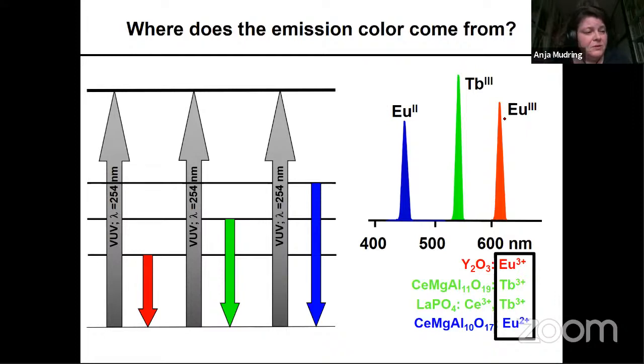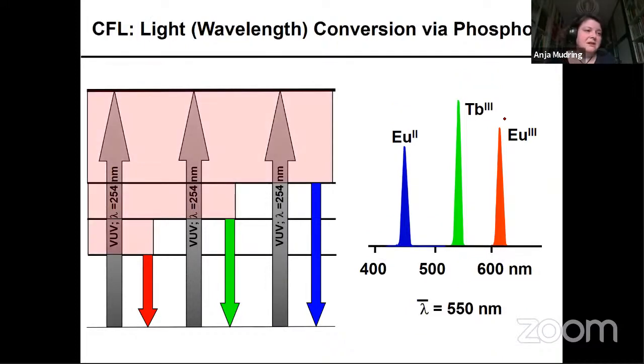And when you look at this scheme alone, you see, and I try to depict it somewhat graphically, you're converting high energy UV radiation into visible of longer wavelengths. So you're essentially losing a lot of the energy you've put in. Here shaded in red. The worst is for the red photons you're generating. You see, you're putting much more energy inside than you get out with the red light. If you just take the average and say the average of visible light is 550 nanometers, you can estimate that you lose, even with that energy efficient light bulb, 60% of your energy in the conversion process. It's still a lot more efficient than the incandescent light bulb, but by no means really energy efficient. We have to be aware of that.